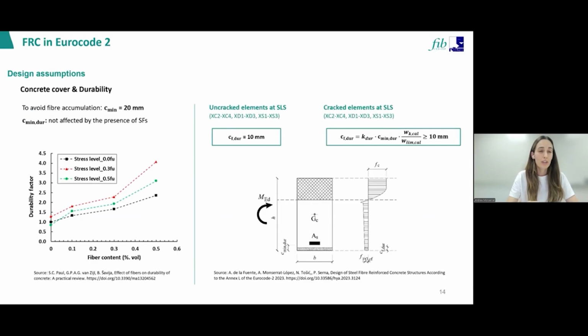And finally, about the design assumption related to durability, it's true that Annex L adopts a relatively conservative approach. Actually, the minimum cover required for durability is generally considered unaffected by the presence of steel fibers. This means that any potential durability benefit associated with the inclusion of fibers is neglected in the code provisions. Nevertheless, steel fiber reinforced concrete surface layers are still vulnerable to deterioration.